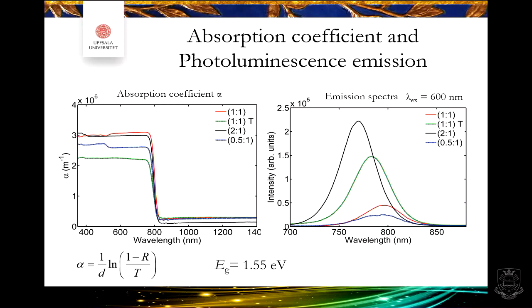Here we see the highest intensity of this emission, and the intensity in photoluminescence emission gives you information of how good this material is. If you have put it on a glass or something, so the electrons are not going further into another material, there is no quenching, as it's called. This emission peak and the intensity of that is also giving you information of how good your material is, one can say. And here you actually see that the one that has more MAI in the solution was the one that functioned best. But here there is not that much difference. The band gap is still sitting at the same place.